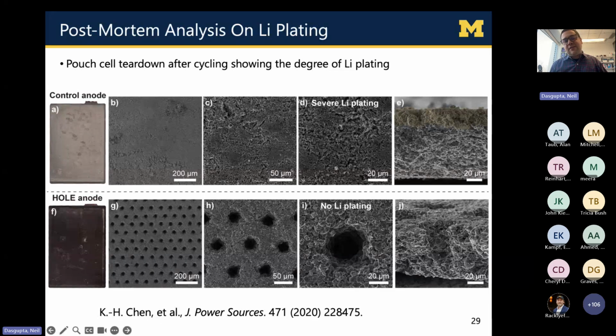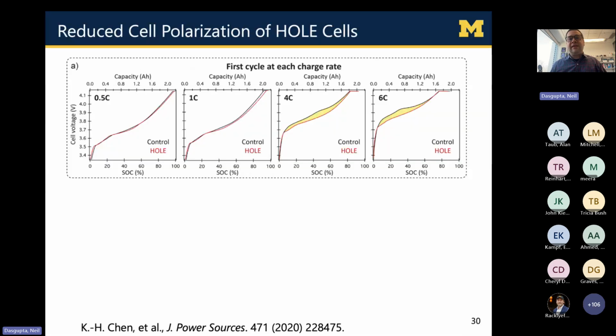On the other hand, after the hole patterning, what you can see is that we've eliminated lithium plating, even after hundreds of cycles of 6C fast charging. We can see that the hole structure remains intact, and we're able to really charge and discharge this battery at a fast rate without that lithium plating occurring.